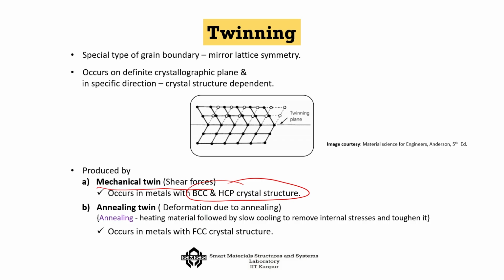So, one particular material which shows this twining and plays a very important role in the memory is called the shape memory material, which is an alloy of nickel titanium. If you cool it from the parent state, austenite, then you will get these self adjusting states or the twine states at the martensite state, and this happens for the shape memory alloys or SMAs.